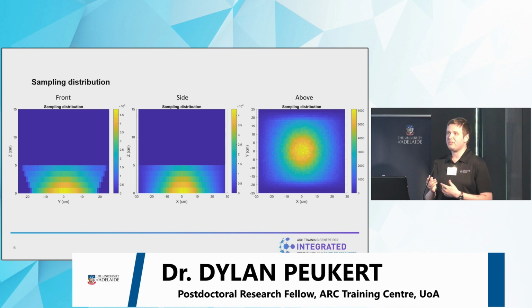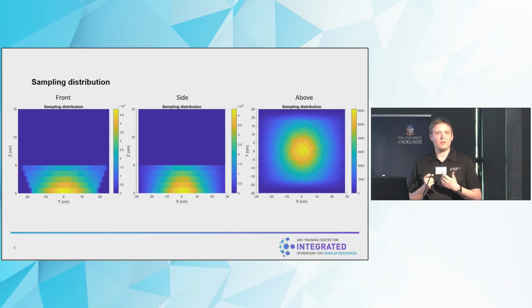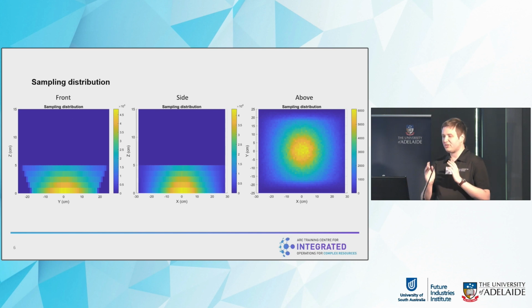So taking a look at the first of these characteristics, the simulation can record the origin point for every recorded photon, which enables the sampling distribution for the tested material to be determined. Here we can extract the 3D distribution, and we show 2D profiles from the front, side, and above. It is possible to see that the sampling is stronger towards the center and towards the base, which is closer to the isotropic neutron source. However, a high level of sampling is achieved throughout the entirety of the material, in this case a 5 centimeter thick iron oxide copper gold model, which enables the reduction of biases, which is problematic for other sensing techniques which only sample a single point or a surface.